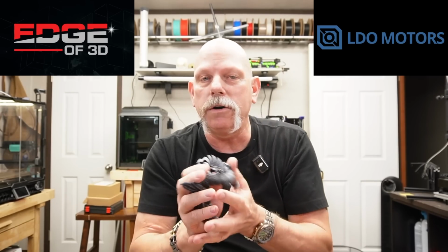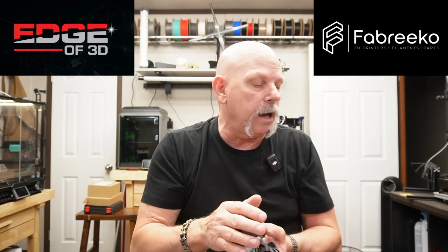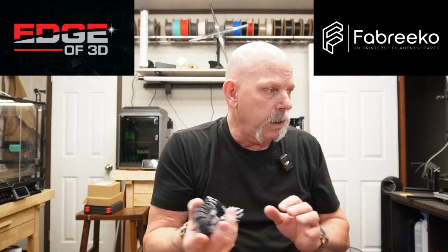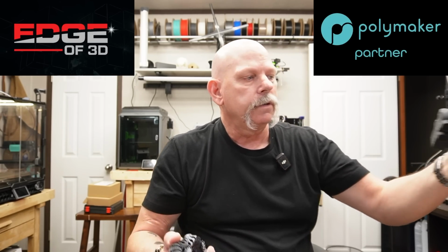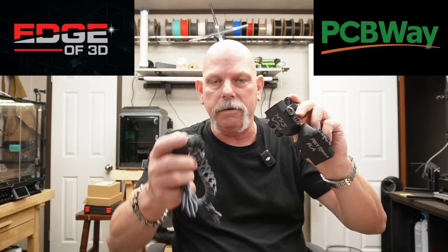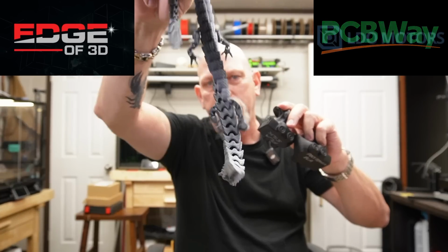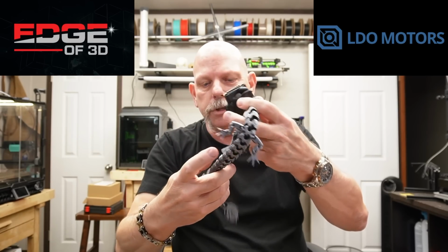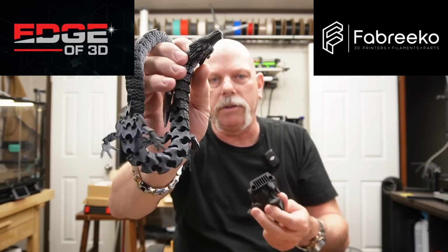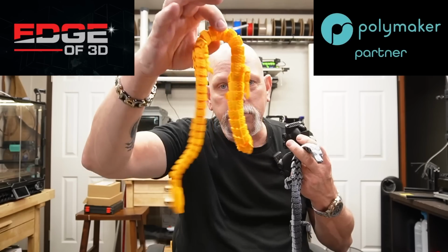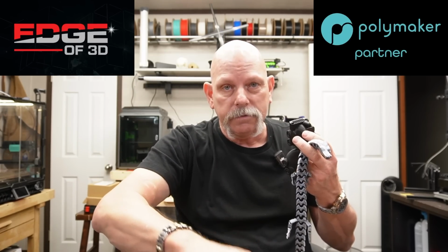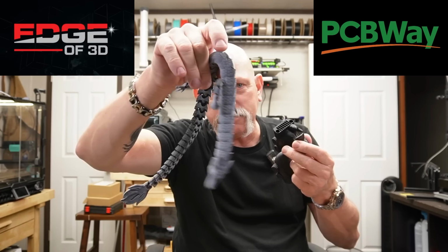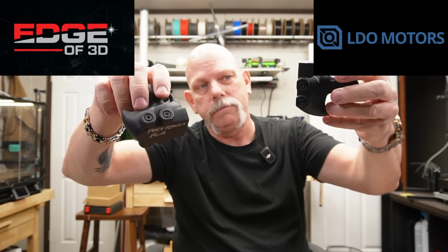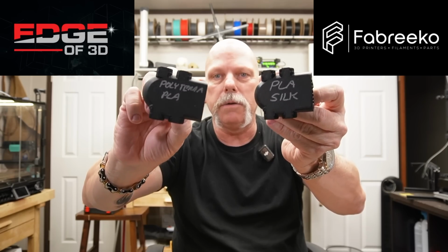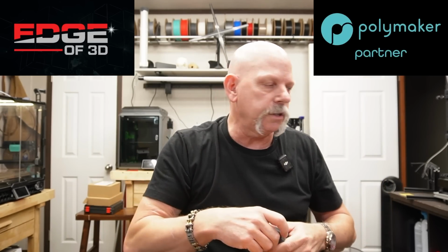So I'm going to do a lot more temperature testing on PLA. I want to get to the bottom of this. But we had some PLAs that were surprising. Silk and Polyterra PLA. This is just regular PLA. Everything's perfect on this dragon. These dragons were heat treated. Okay, this dragon was not. Take a look at that. These ducks were not heat treated. PLA Silk, Polyterra PLA, 150 degrees Celsius.